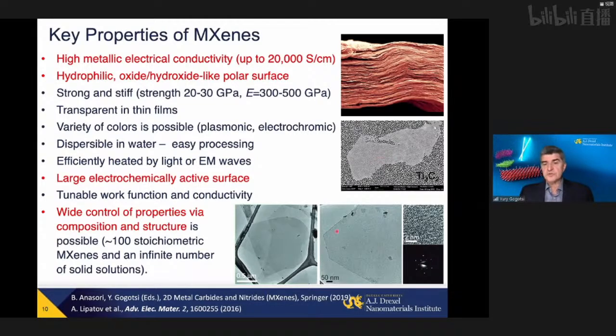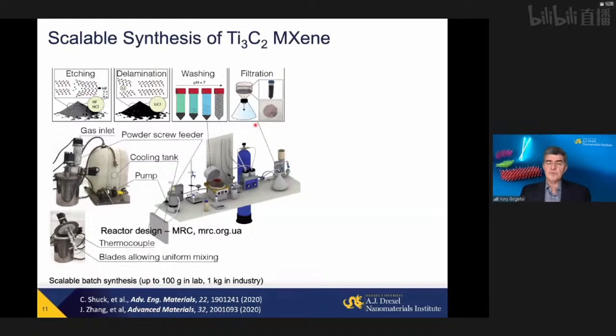Otherwise, these flakes look like flakes of many other 2D materials. You see, for example, a hexagonal imprint of the structure. Those are single crystals. This is a single layer, single crystal Ti3C2. This flake is about 20 micrometers in length. And you can pack thousands of those flakes into this type of structure, similar to, say, graphene or graphene oxide paper. And it's all possible.